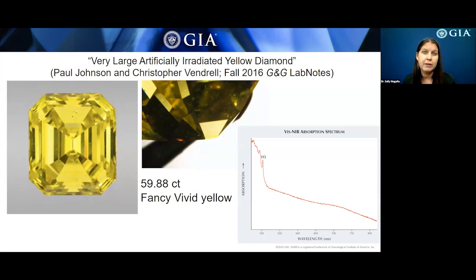It was examined at the New York laboratory, and although the face-up color distribution appears very even, the authors observed a moderate color concentration along the culet. And this is often seen in laboratory irradiated diamonds. Because of the risk of damage, diamonds subjected to this treatment are typically less than 10 carats, whereas this one is 59.88 carats. Laboratory irradiation, perhaps with subsequent annealing in order to enhance color or change color, is one of the oldest diamond treatments available.